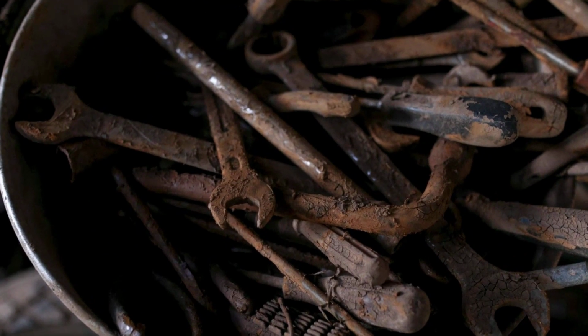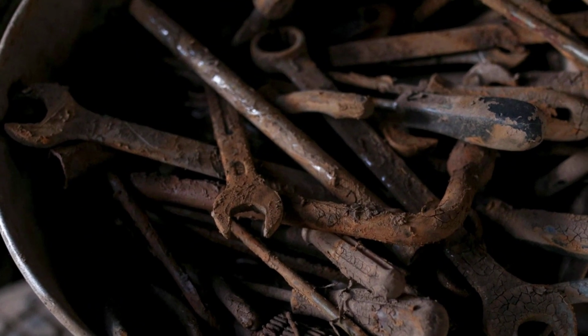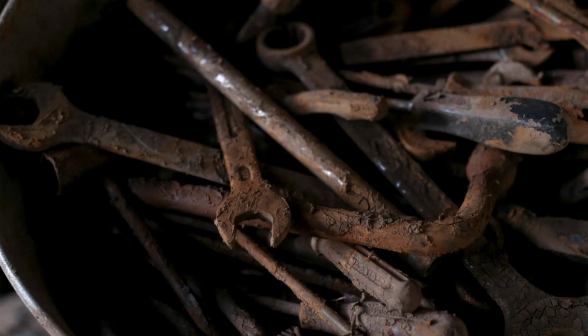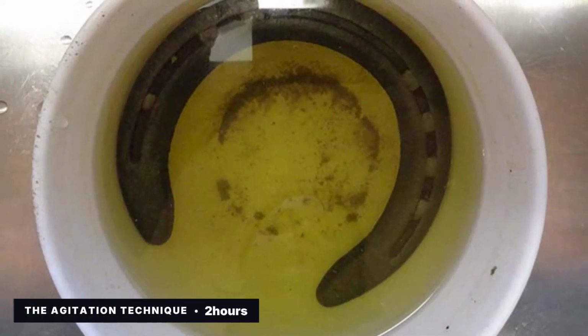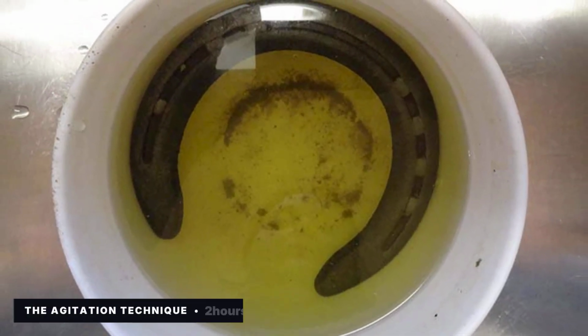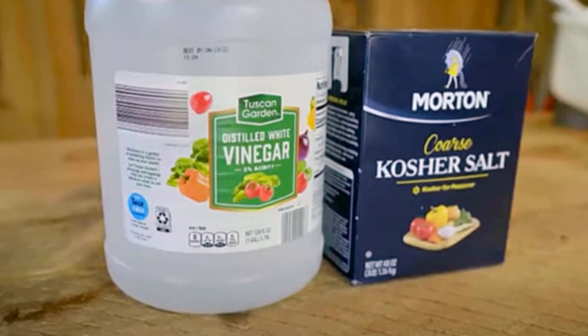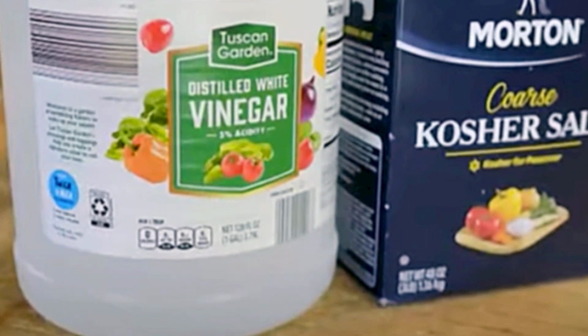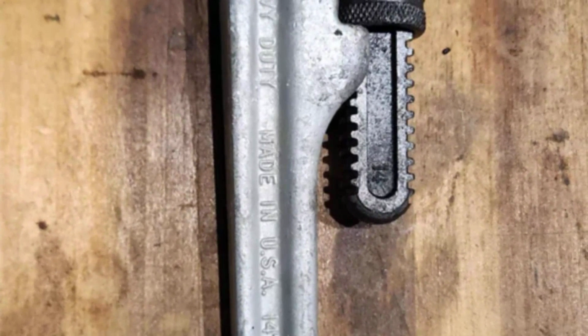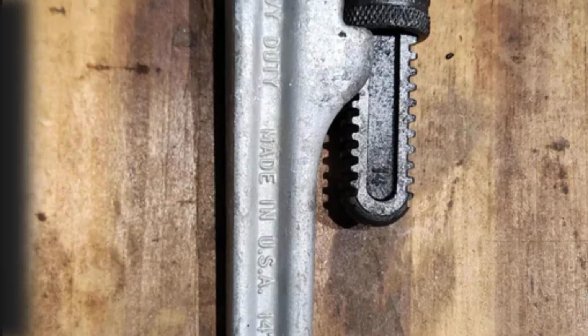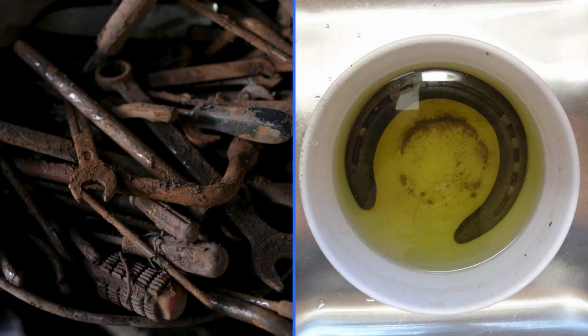Now the part mentioned earlier. Every 2 or 3 hours, lift the tool out, let it drain for a few seconds, and put it straight back in. As the rust dissolves, it leaves behind a soft black layer on the surface, and that layer sits there and blocks fresh acid from reaching the oxide underneath. Lifting the tool disturbs it and lets the liquid get back to work. Without that, the reaction slows down badly after the first few hours, and you will wake up to a tool that is only half done.